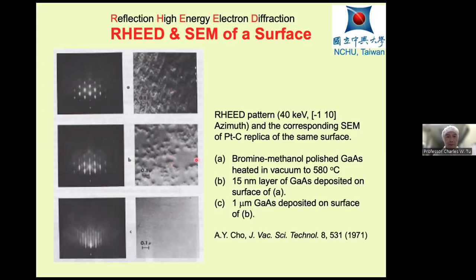Then the middle two slides are after growth of 15 nanometers of gallium arsenide. You see the surface becomes smoother, and the electron diffraction starts to be a streaky pattern, meaning that we are going from 3D to 2D diffraction. And then after 1 micron of growth of gallium arsenide, you see the surface is very flat, and here we see a two-dimensional electron diffraction. This diffraction is streaky because the third dimension is not defined. And so we use this electron diffraction to monitor the surface.